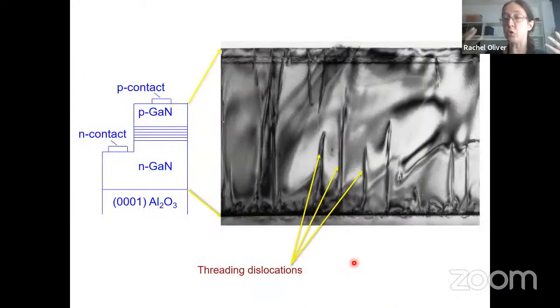This is now a more zoomed out transmission electron microscopy image, looking at a light emitting diode, a very simple light emitting diode in cross section. And we've got P-type gallium nitride at the top, N-type gallium nitride at the bottom, and in between the quantum wells. But running through now, we can see these dislocations as lines. So in the previous images, we were looking down the end of the dislocation line and the line was into the page. Here, we're looking at the actual lines themselves from the side, and we can see they come up all the way through the device.